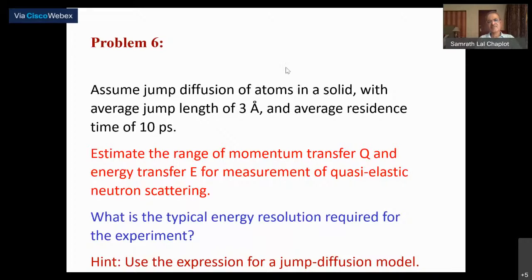It can be even smaller than that if yours is a more dense material, with more density of hydrogen. But typically it is in the range of a millimeter or less for hydrogenous materials, or it could be a few millimeters, maybe say 5 millimeters, for other materials. That is the kind of sample thickness you would use. You can actually calculate the thickness you should use so that you get only around 10% single scattering. Therefore the probability for a double scattering would be something like 1%, and that can be neglected.